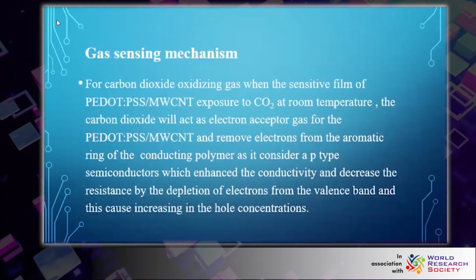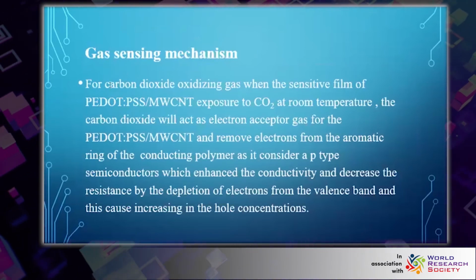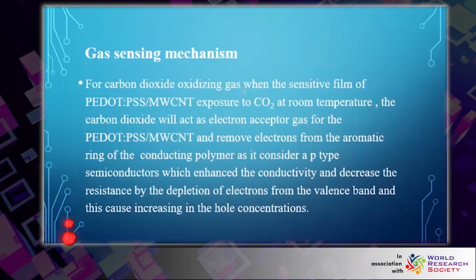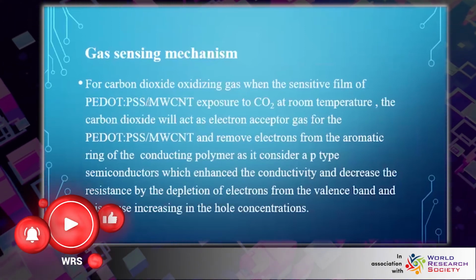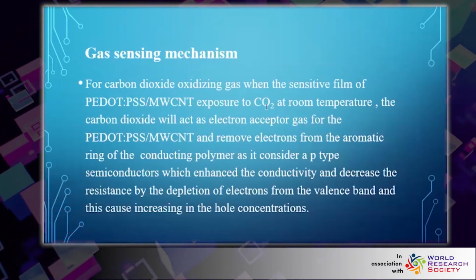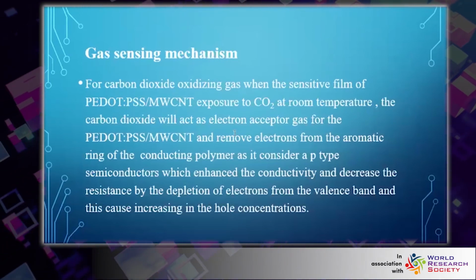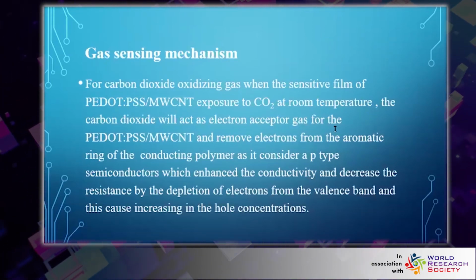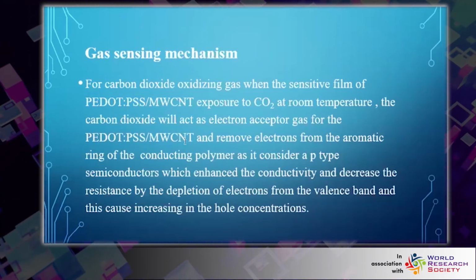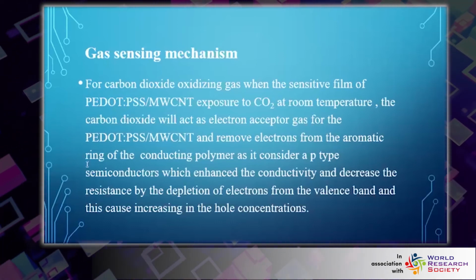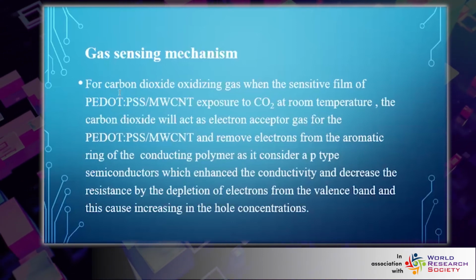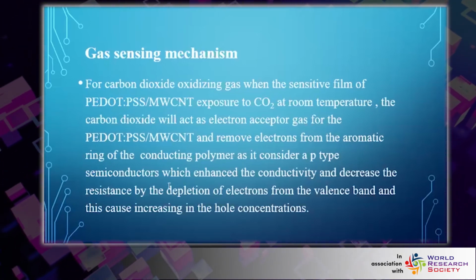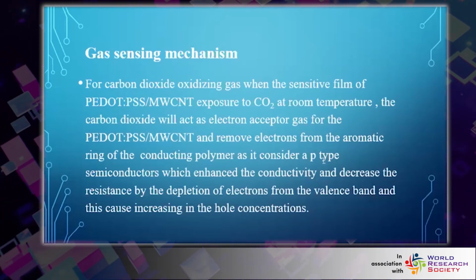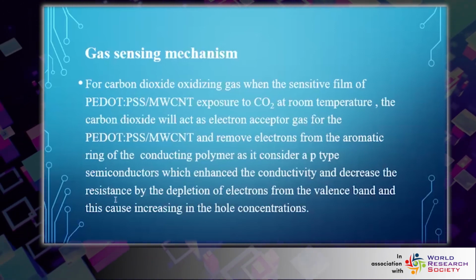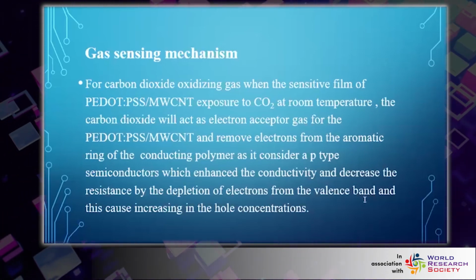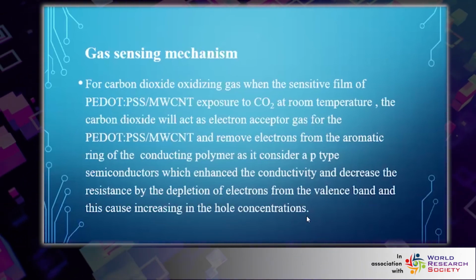About the mechanism of gas sensing for my gas sensor: carbon dioxide is an oxidizing gas. When the sensitive film of PEDOT:PSS multi-walled carbon nanotube is exposed to carbon dioxide at room temperature, the carbon dioxide acts as an electron acceptor gas for the PEDOT:PSS multi-walled carbon nanotube and removes electrons from the aromatic ring of the conductive polymer, which is considered a p-type semiconductor. PEDOT:PSS is a p-type semiconductor, which enhances the conductivity and decreases the resistance by the depletion of electrons from the valence band, and this causes an increase in the hole concentration.